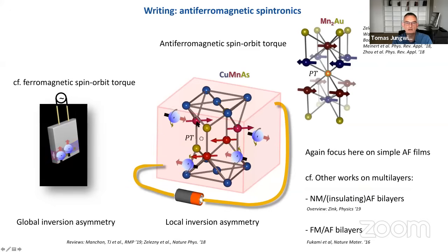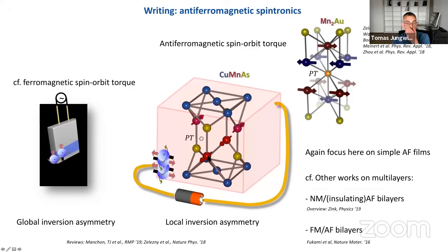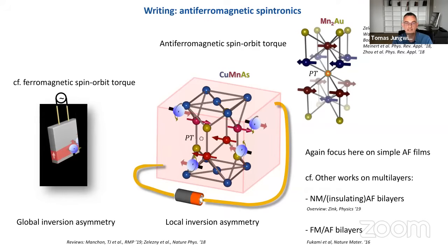So these two sites are inversion asymmetric positions of atoms, and the breaking of the inversion symmetry has an opposite sense. This is another way of saying, in fact, that this crystal has the combined PT symmetry. So the very same PT symmetry that allowed us to have in principle the Dirac points now also allows us to electrically control the direction of the antiferromagnetic moments, which in the ideal world would allow us to control the opening and closing of the gap of the Dirac point, for example.